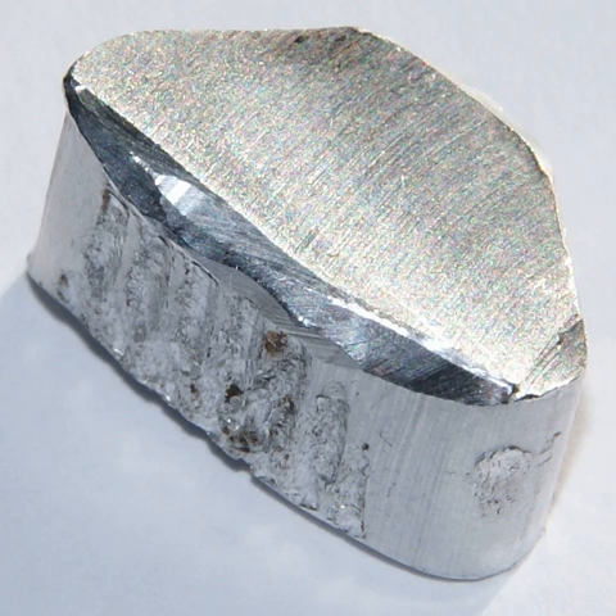Recycling. Recovery of the metal through recycling has become an important task of the aluminium industry. Recycling was a low-profile activity until the late 1960s, when the growing use of aluminium beverage cans brought it to public awareness. Recycling involves melting the scrap, a process that requires only 5% of the energy used to produce aluminium from ore, though a significant part, up to 15% of the input material, is lost as dross, an ash-like oxide.